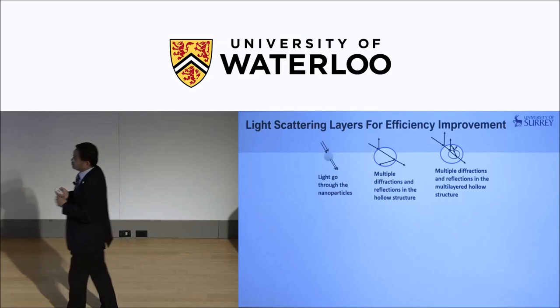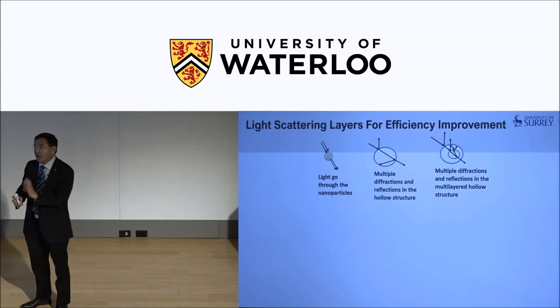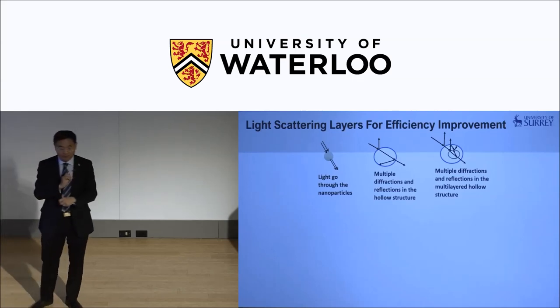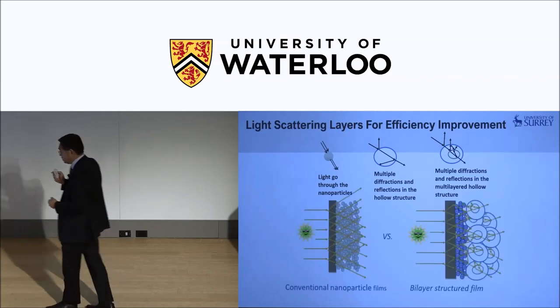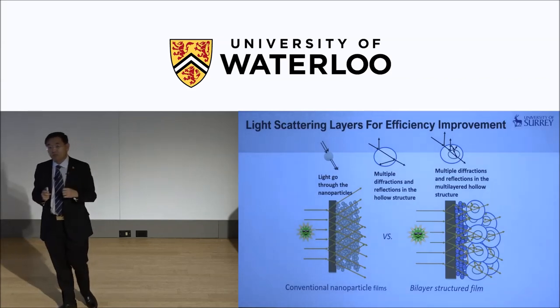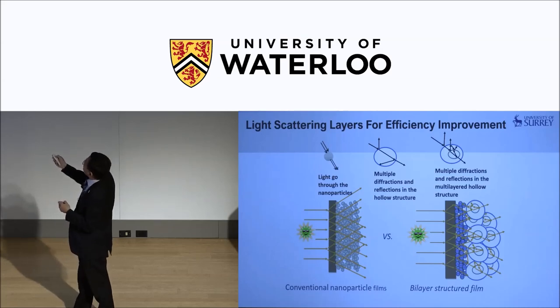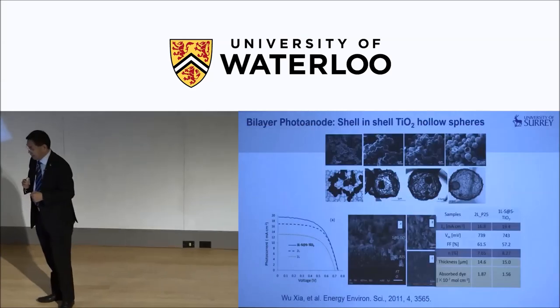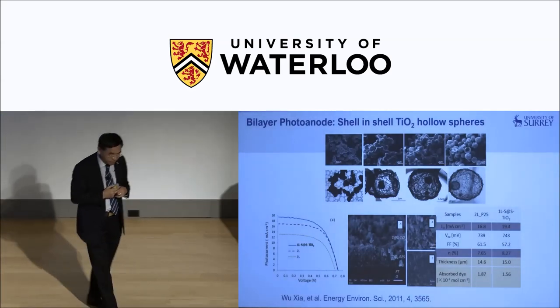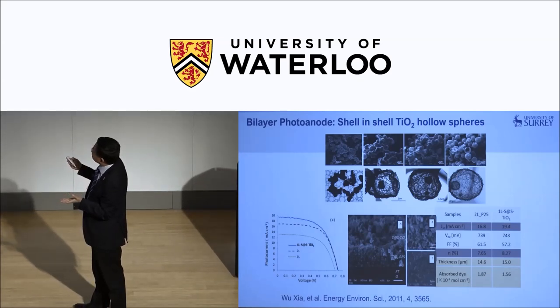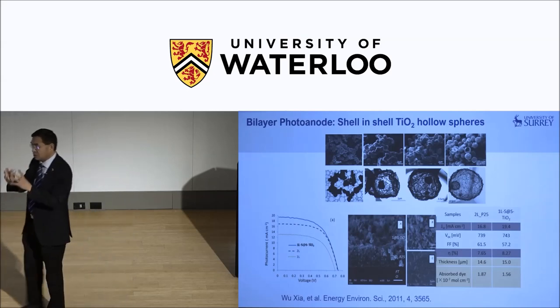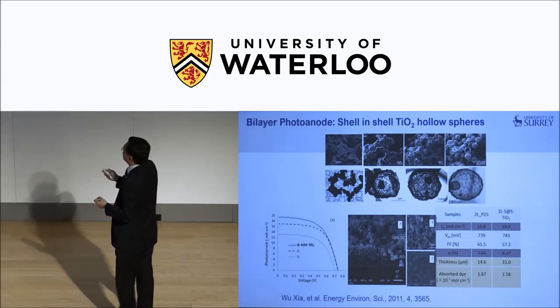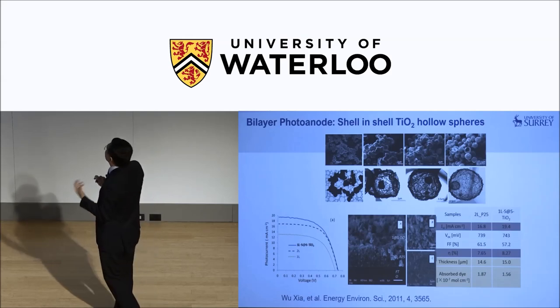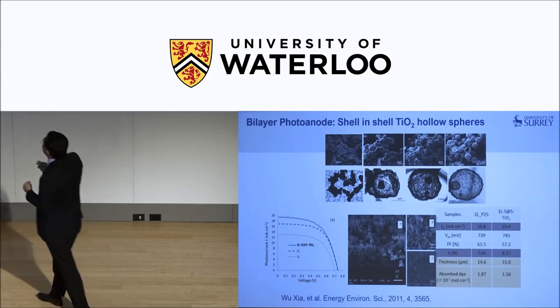But this work we did is trying to demonstrate the light scattering, how to enhance the light scattering, and therefore the light harvest efficiency and then conversion efficiency by using the fluoride-directed single crystal but a hollow sphere to make a multi-layer photoelectrode. So basically the mechanism is that if you have hollow spheres, you trap a lot of light, a lot of multiple scattering of light, and the idea is to enhance the light utilization. And this simply demonstrates a one-pot synthesis using sugar as a template, and then you put these nanocrystals to form a hollow sphere in one-pot synthesis, and you make a double layer. This is only a double layer compared to the single layer. You can see there's a noticeable improvement in the efficiency.